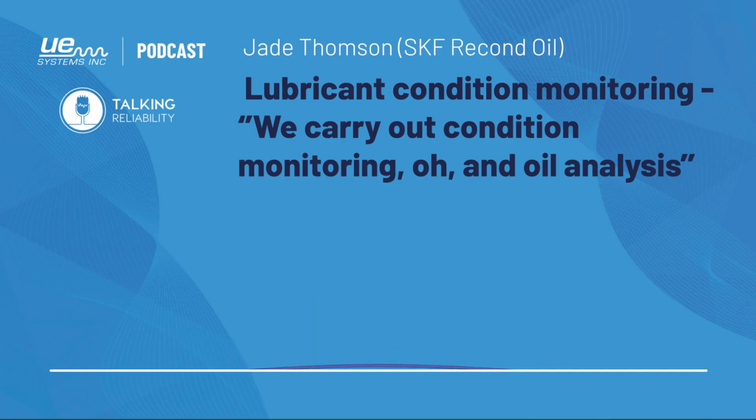And this is in the rail industry, but this was one train that we can see on the top graph. Luckily, we're getting weekly analysis. So we very quickly decided, let's speak to the rail customer. And we said, Mr. Customer, you're using a different additive pack. That's because we've got really high phosphorus. And that's affecting copper in the system.